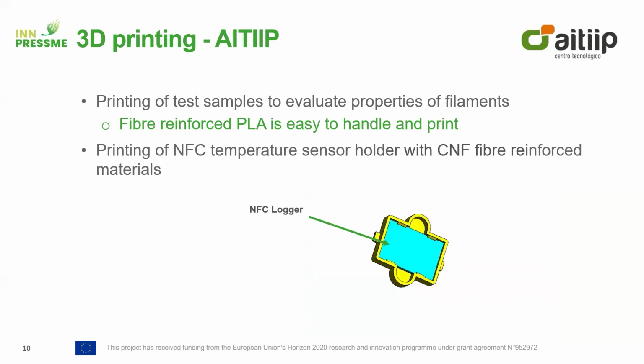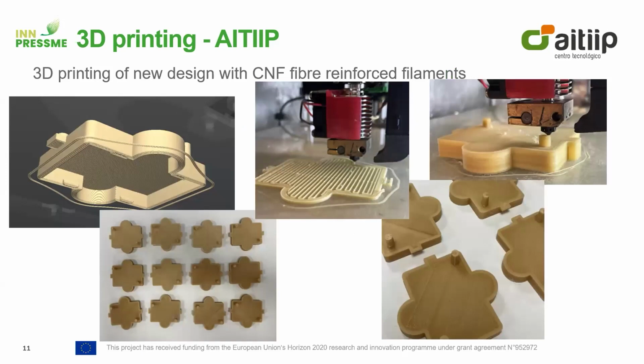With regards to the next steps, the first part of the demonstrator, we had partner AITIIP, who produced a special part which was not suitable to make it with injection molding. It was a holder for an NFC temperature sensor, and AITIIP did different tests with the filament produced by IPC and stated that the fiber reinforced PLA was easy to handle and to print. And so they printed various versions of this holder of the NFC logger. Here you can see a few images from the design of the holder over the printing process and then to the final components that were made for the demonstrator production.